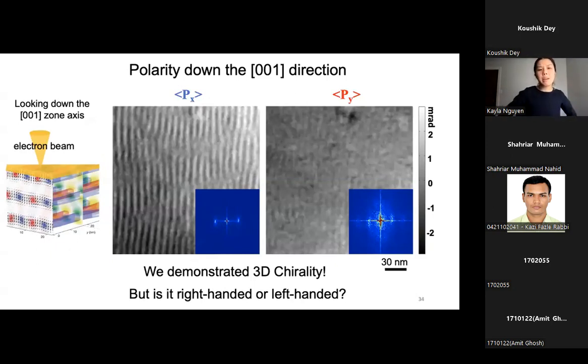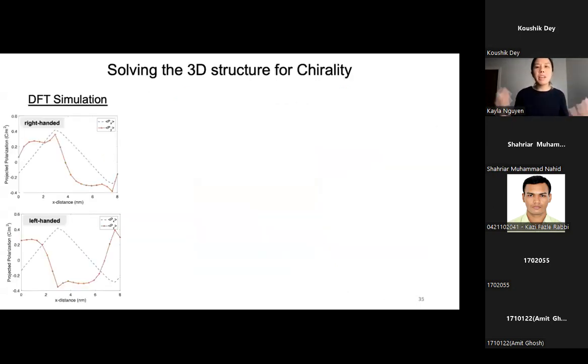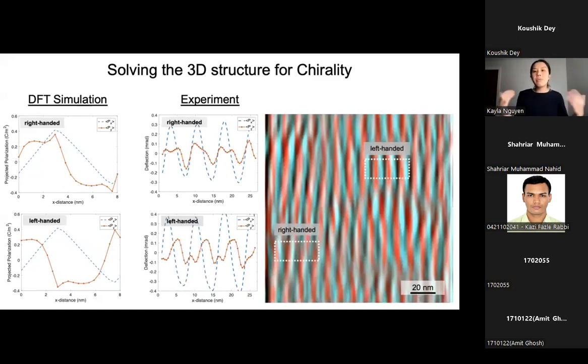So then the question becomes, is our sample right-handedly or left-handedly chiral? To solve that, we go back to DFT simulations of these polarization structures, and we can sum them up in the projected direction. We find that if our sample is right-handedly chiral, Px and Py lie directly on top of each other. If it's left-handedly chiral, they're 180 degrees out of phase. If we overlay our Px and Py images on top of each other, we find that there are regions of the sample that are right-handedly chiral, and regions that are left-handedly chiral.